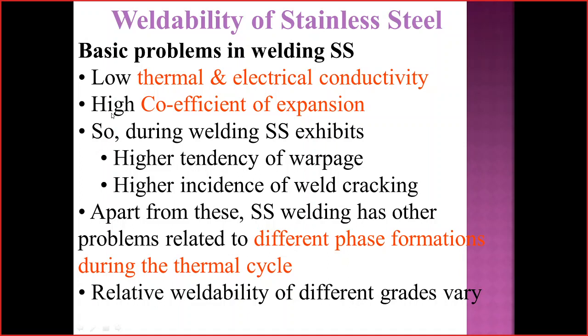Okay. And the third problem is the high coefficient of expansion, which is a property of the material stainless steel. For this purpose, we have to keep our electrode while depositing a little bit more than in our conventional arc welding. So during SS welding, it exhibits a higher tendency of warpage, a higher incidence of weld cracking, and also other problems related to different phase formations during the thermal cycle. So the phase formation will be disturbed.